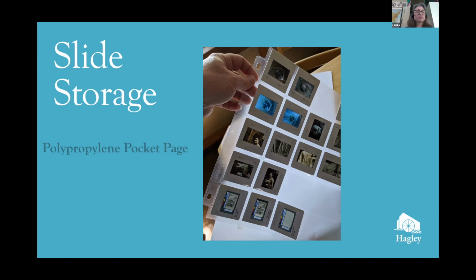It's very important to avoid the use of polyvinyl chloride plastics, also labeled and called PVC, because this plastic releases sticky plasticizer as well as hydrochloric acid. The plasticizer can dissolve inks and it will adhere to the photographs inside. You should purchase pages made of polypropylene from reputable preservation suppliers. If the plastic has a vinyl shower curtain smell, you should avoid using them.